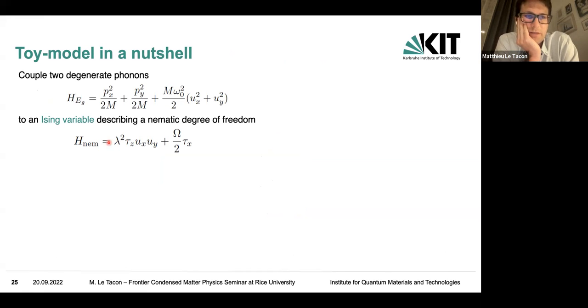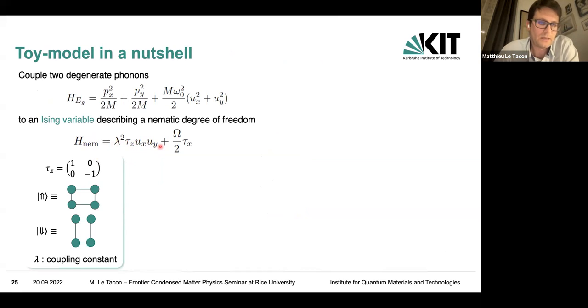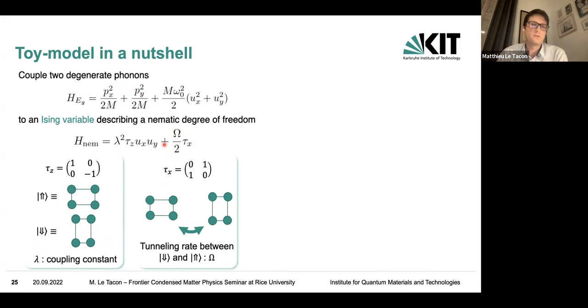And basically he came up with a toy model. So he said, well, you take a doubly degenerate phonon, and you couple this to an Ising variable which describes a nematic degree of freedom. So in short, you have this operator here, this Pauli matrix, which describes basically two states, and there would be these two orthogonal atomic distortions. So you call that the spin up, and you call that the spin down. You can have a coupling constant of this distortion with the phonon mode. So that's this lambda constant, and then you put in some fluctuations. So that's basically a tunneling rate between the two configurations at a given frequency omega.